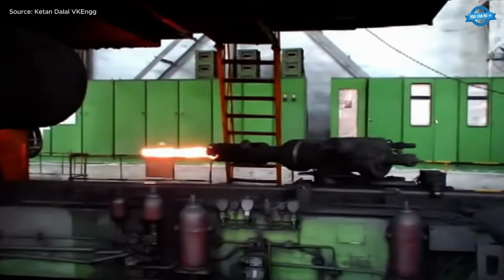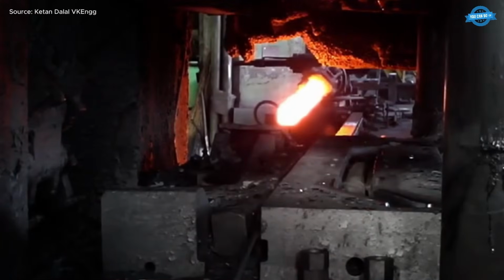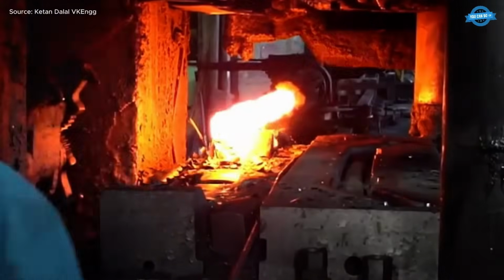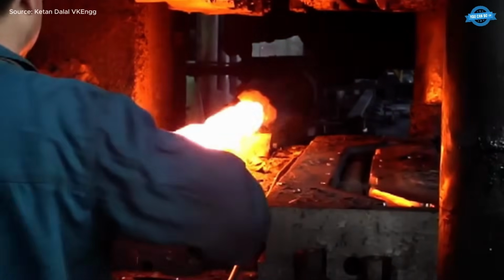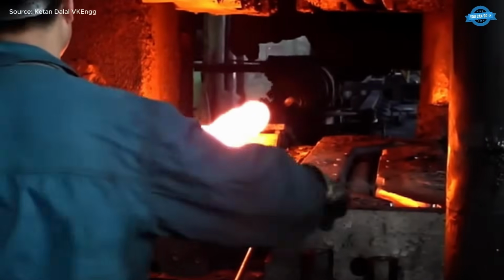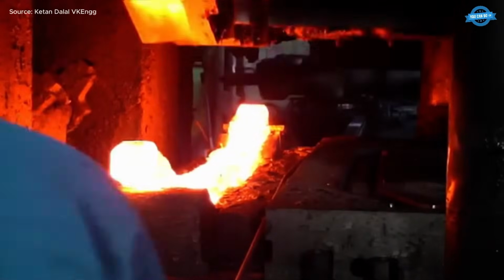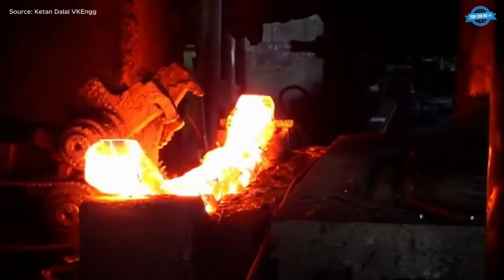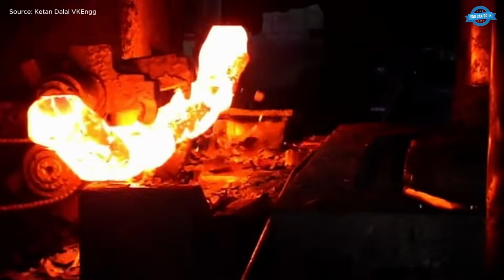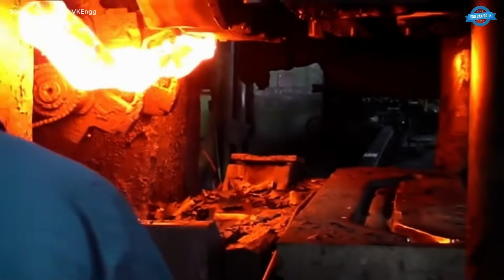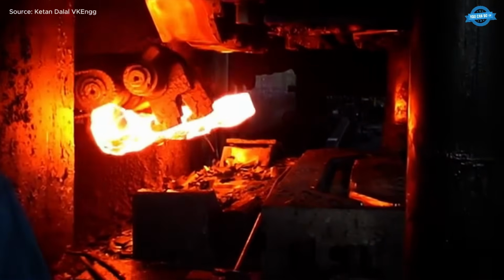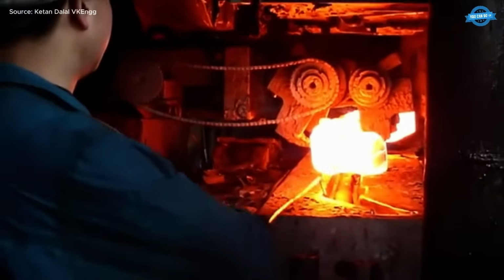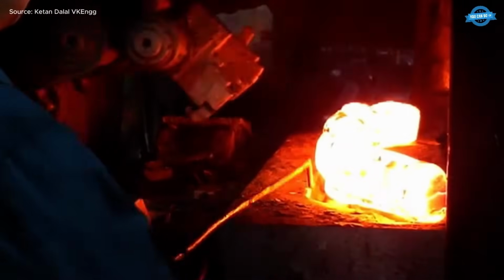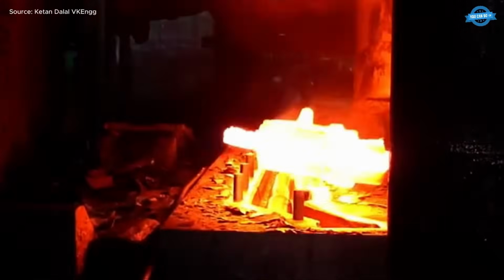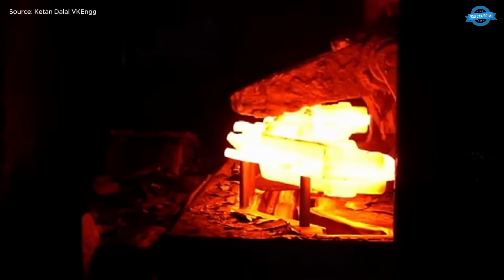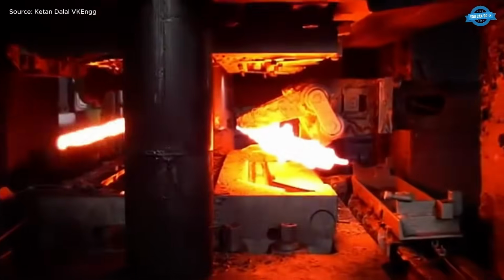These billets are then heated uniformly in induction furnaces to around 1,200 degrees Celsius to achieve the necessary plasticity for forging. Once heated, the billet is transferred to the press, where a powerful 12,500-ton hydraulic press shapes it into the desired form using custom-designed dies. The forging may involve a single or two-step process, including pre-forming and final shaping. After forming, excess material or flash is removed at the trimming station. Controlled cooling follows, using either slow or forced methods to prevent defects and ensure structural integrity.